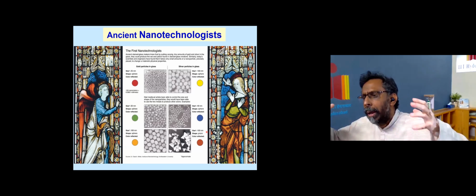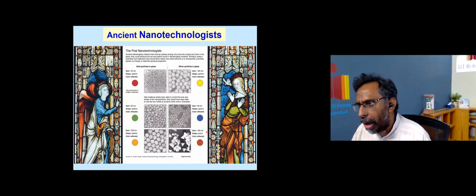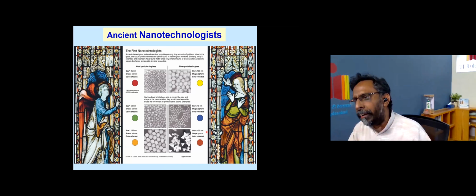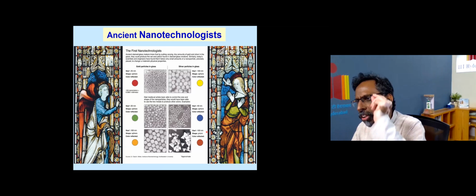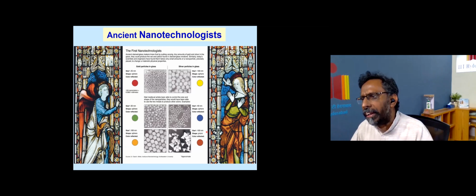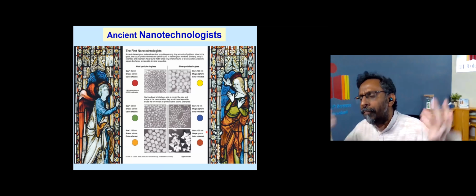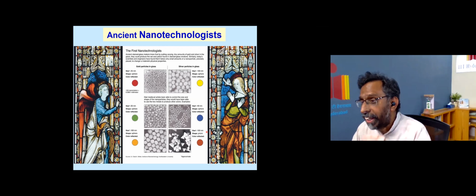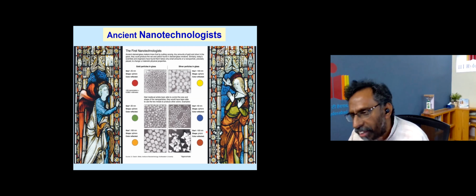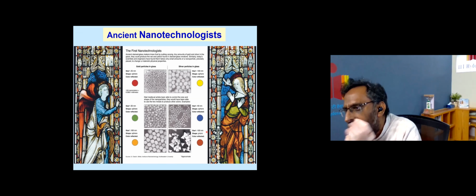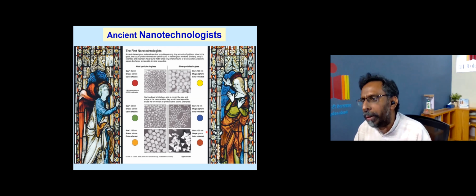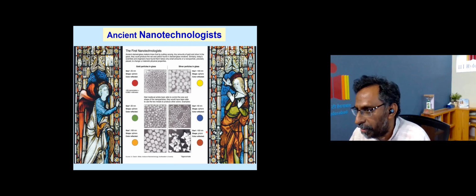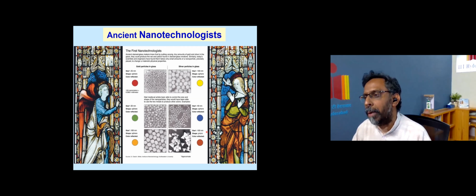For example, take a big boulder and break it into small things. Or go to Marina Beach, simply pick up the sand and look at the sand particles. Each particle is of the order of around a millimeter in size, or maybe half a millimeter. If I take that powder, put it into something like a Sumeet mixie, and grind it to very fine size, such that the particle becomes, let's say, 100 nanometers, 50 nanometers, 20 nanometers, 10 nanometers, what happens? You see fantastic changes in properties.